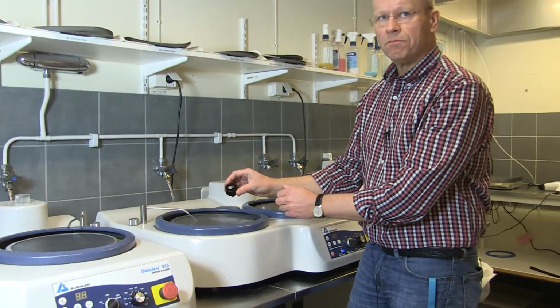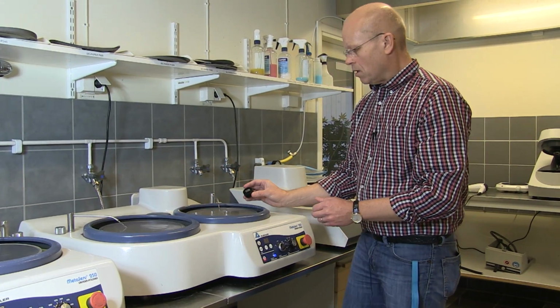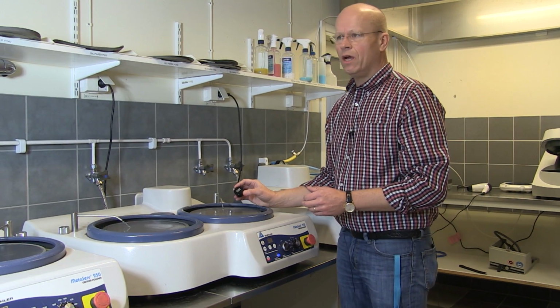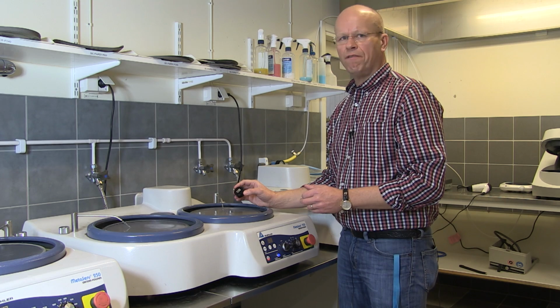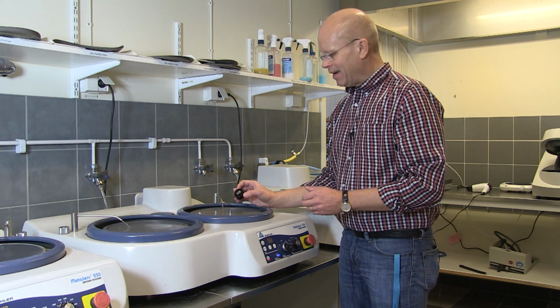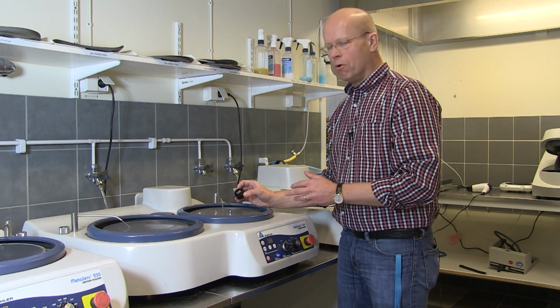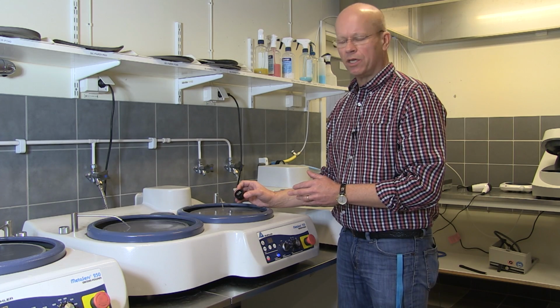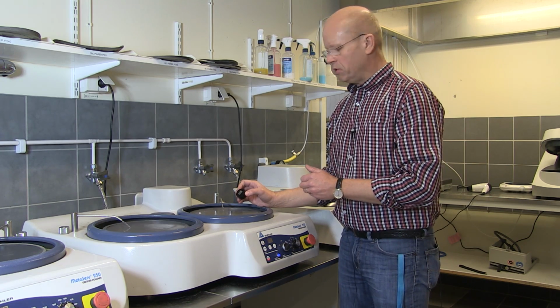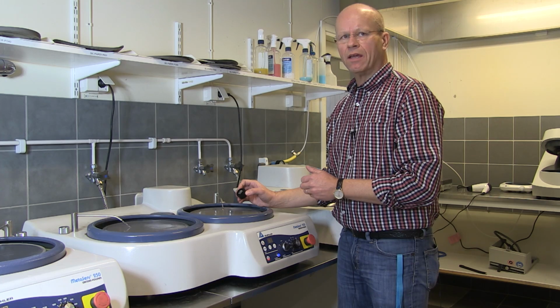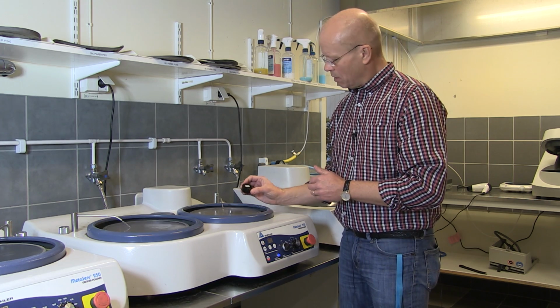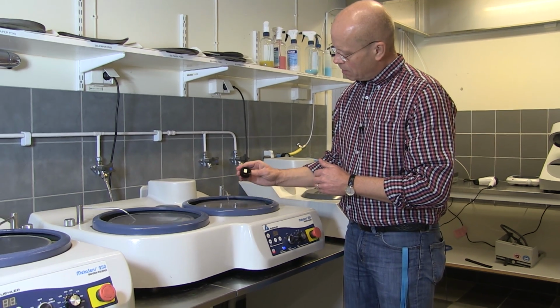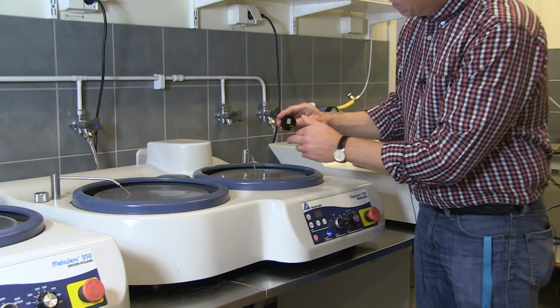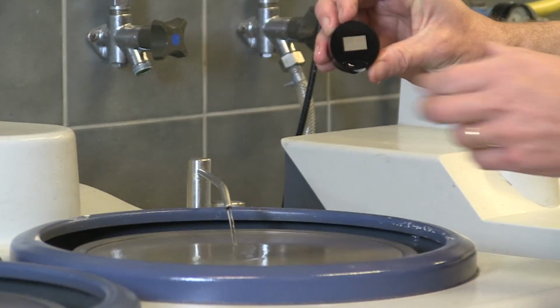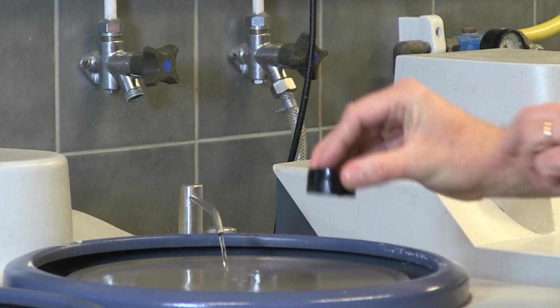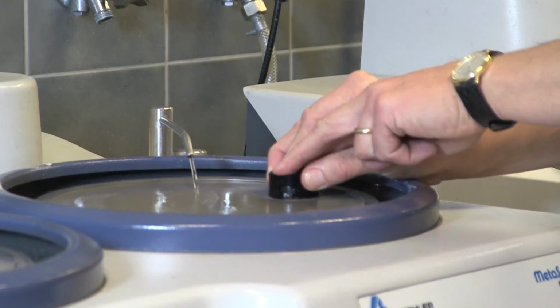To the next step, which I will do on P1200 paper, and P1200 is 15 micrometer. It might be possible to jump over this step before you go to polishing on cloth, but I usually do this grinding step also and think that I save some time on that. So coming here, with scratches coming in that direction, I rotate the sample 90 degrees and put it down and grind again.